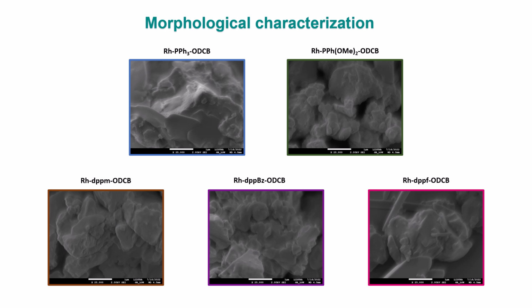SEM images revealed heterogeneous morphologies composed of irregular agglomerates. Differences in particle texture and aggregation suggest that the phosphine ligand also affects the morphology of the supported catalysts, which may contribute to their electrochemical performance.